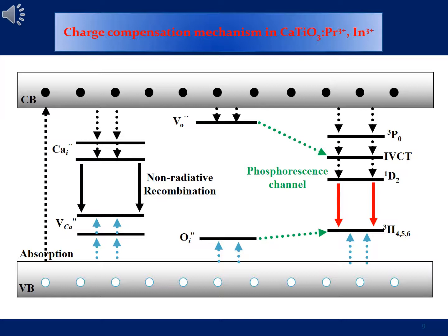And now the most important electron trapping centers for us will be those of oxygen. Now, because oxygen is negative, its interstitial defects will reside at the acceptor level, and the corresponding vacancy, which are positive, will be at the donor level. Now, this is very important to us in that these electrons which are trapped, they may be released back to the conduction band, depending on the depth of these oxygen vacancies. Some are deep, some will be shallower, close enough to the conduction band such that the electrons trapped can be stimulated back to the conduction band by the thermal energy of the ambient temperature. Now, that's very important for us in persistent luminescence.